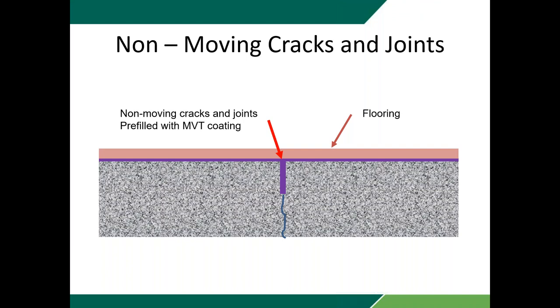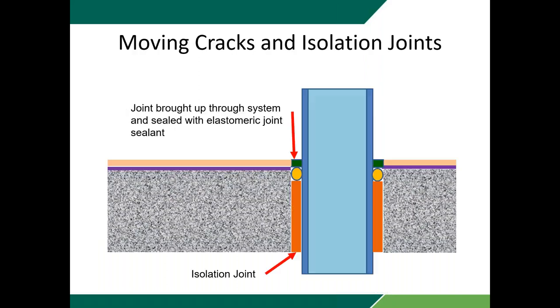When we're dealing with moisture vapor transmission systems, we want to deal with the cracks and the joints in the floor, because those are places where moisture can come up through the concrete. Typically what we do is we come in and we fill those joints or cracks with the actual moisture vapor transmission coating, detail it ahead of time, and then we apply it over the top, and we have basically a seamless moisture transmission mitigating coating over the surface, and then we can apply our flooring to it.